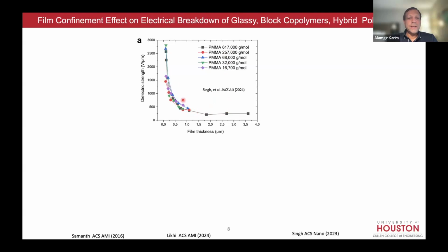So that's great. If you look at the ratio of the thinnest film, which is maybe 150 nanometers, to the 1 micron or 2 micron film, it's about a factor of 10. So 10 times higher breakdown strength. That is actually very impressive because the energy goes as the square of the dielectric strength, which means we should think of 10 squared, which is 100. So presumably an ultra thin film of 50, 100 nanometer has 100 times more energy storage capacity compared to these micron thick films. So this was just recently published.